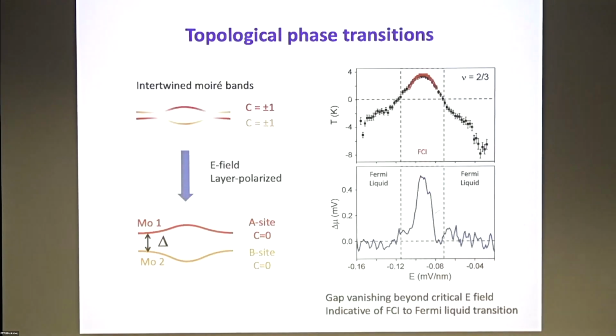Okay, so a final word before closing this topic is that you can also apply electric field to make the bands non-topological, and you can measure the charge gap of that incompressible state. This is the FCI state, the two-thirds filling, and you can actually see that once you apply the electric field, the gap goes to 0, so it goes to a compressible state. Looks like somewhat continuously, and also you lose the ferromagnetism. So this is a part of the Curie-Weiss temperature. Exactly at that critical point, the Curie-Weiss temperature is no longer positive, so you lose the ferromagnetism immediately.